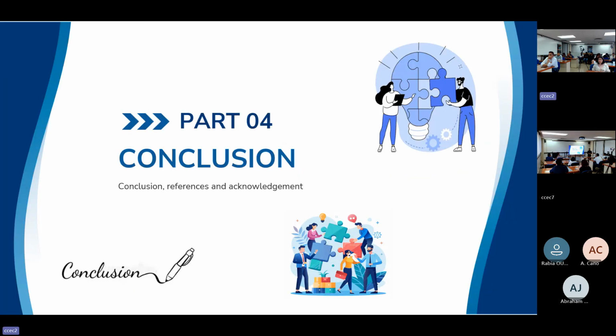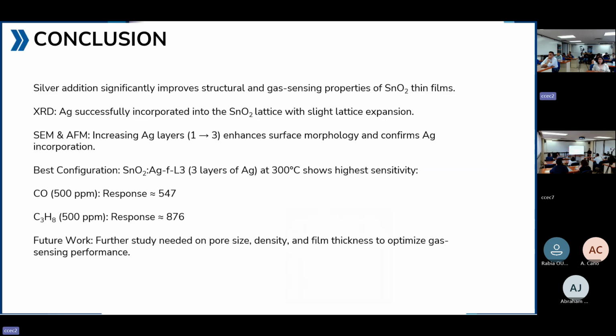So we are concluding all the results we saw so far. We conclude that this work significantly demonstrates how the film is enhanced with the addition of silver, structurally and also in application performance. The comprehensive characterization of the films, structural, morphological, and optical, shows how each immersion of Ag influences the structure's morphology. Finally, the 3-layer Ag added tin oxide coating showed maximum sensitivity at the higher operating temperature of 300 degrees Celsius for both gases: 547 for carbon monoxide and 876 for propane. However, we have to address some questions like pore size, density, and film thickness changing with the addition of Ag, to understand the gas sensing mechanism in depth, which will be addressed in our future work.